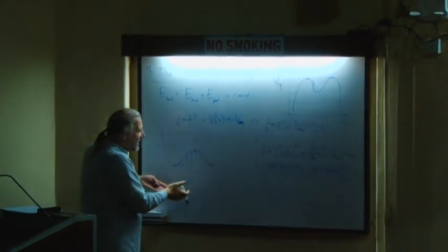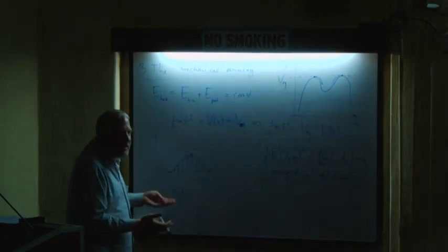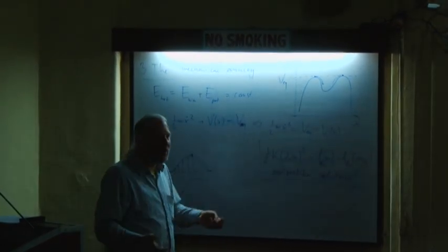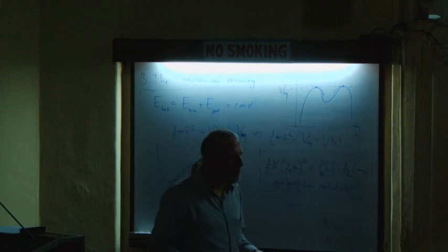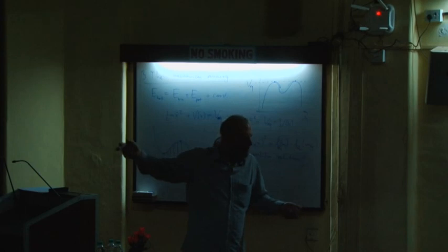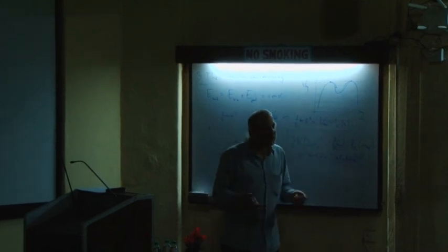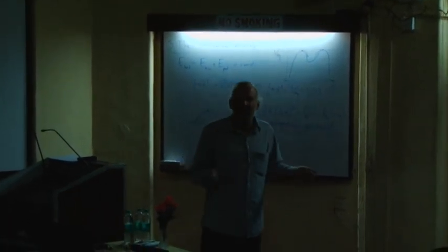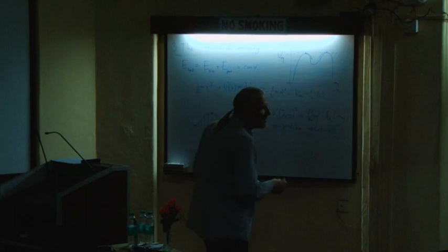So it might not be exactly a hyperbolic tangent, but the interface solution will always somehow look like a hyperbolic tangent. Okay? So it doesn't really matter what kind of double well potential you use. And that's why everybody uses this polynomial, because it's the simplest and because there is an analytic solution. But it's important to understand that this is not limiting. If for some reason you want to use another double well potential, you can. It will not change the physics.